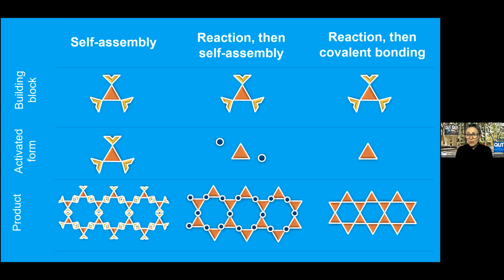For the covalent bonding, what we'll see then is this condensed architecture where we've formed carbon-carbon bonds typically to lock in the covalent structure. And this is really good from an electronic point of view. This will allow us to have fairly long conjugation lengths, that sort of thing, if we're looking at a conjugated system. What I haven't indicated here is how typically this also locks in defects for us. So we tend not to get the perfection out of this approach that we do out of self-assembly, where there's an intrinsic reversibility available to us.